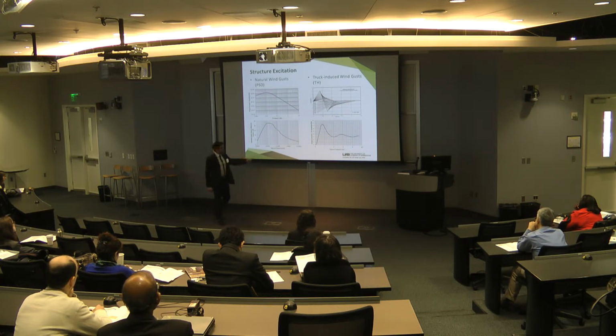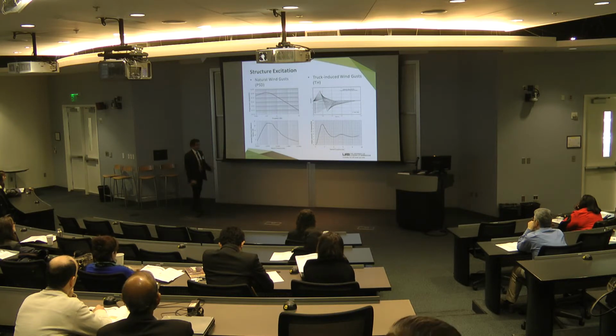And for truck-induced wind gusts, the frequency between 1 and 3 is in this zone. We need to shift away from the peak. The peak is around 1.7 hertz, either increasing or decreasing, okay?